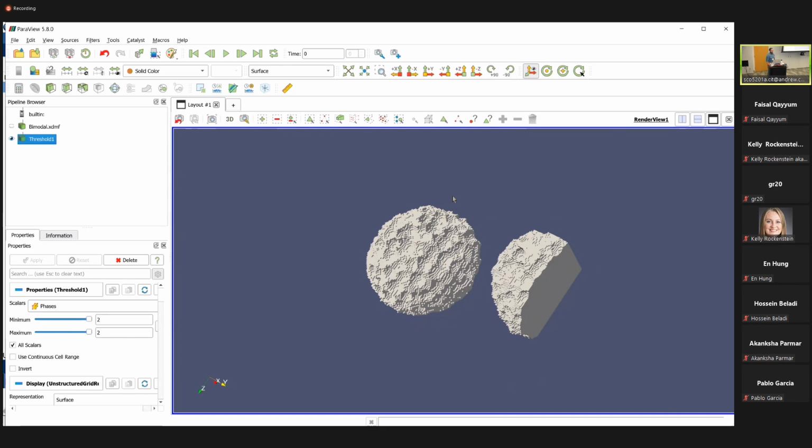It's not that we don't have, I would say, first order, like in Dream3D, you can create geometrically what kind of looks like lath structures. The problem is the complexity of how to make the original parent phase is hard. In general, we don't know what the parent phases look like unless we use a code to reconstruct the parent phases from data that we have collected experimentally, and then we get a sense of, oh, this is generally what the parent phases look like.